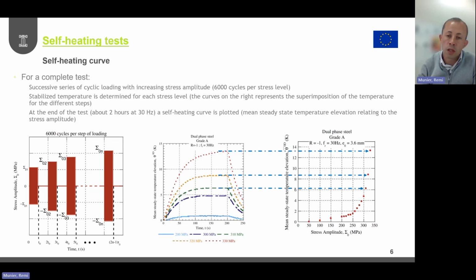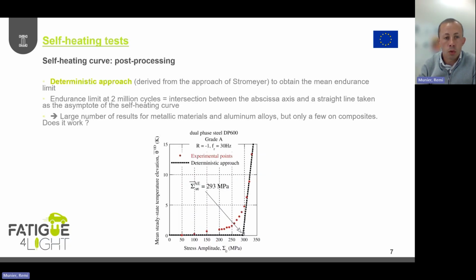And then we measure the stabilized temperature, which permits us to plot, on the right, what is called a self-heating curve, representing the evolution of the temperature of the specimen according to the stress amplitude. Okay, so we have one curve. So what can we do with this curve?